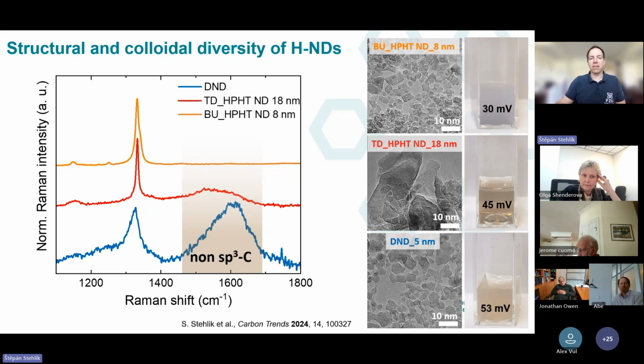But we always see a little increase of the sp2 carbon after the hydrogenation. So this thermal hydrogenation is actually responsible for this increase of the sp2, and that's why we don't see it here. And also, this is the difference to the bulk hydrogenated diamond, which has the negative zeta potential, but it's typically hydrogenated by plasma. And by plasma, you can achieve very clean, very nicely hydrogenated surface without any sp2 possibly. And that's why it has so different properties. So that's why here we have the two factors for this positive zeta potential, the hydrogenation itself, but also the surface disordered sp2 whatsoever.